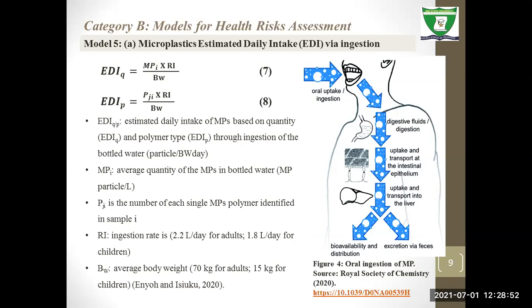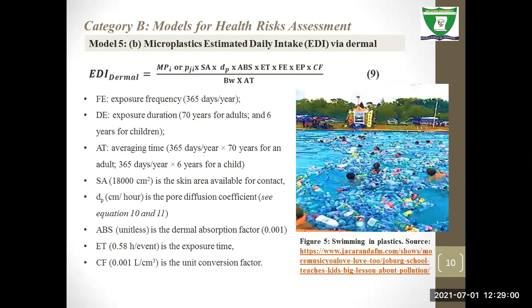From the estimated daily intake, we can also calculate it via dermal exposure. People swim in water that's contaminated by microplastic, and this could expose them to microplastic through skin contact. So equation 9 is used to estimate the daily intake of microplastic via dermal routes. The MPI is already established, which is the quantity of microplastic identified in the sample. The PJI is the microplastic type, whether PE, polyethylene, and so on. The SA is the skin area available for contact. This data can be found from USEPA. The ABS is the dermal absorption factor, which is 0.001. The ET is the exposure time. The CF is the unit conversion factor.